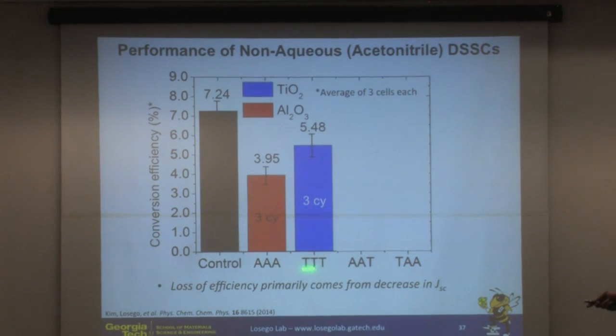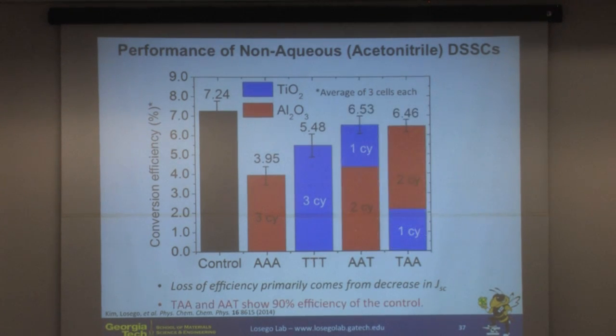So this is the pure case. However, if we now do mixtures, so we did a couple different ways we did mixtures, and this is two cycles of alumina, then one cycle of TiO2, or we reverse those, we can actually get within 90% of the initial efficiency of the unmodified device.